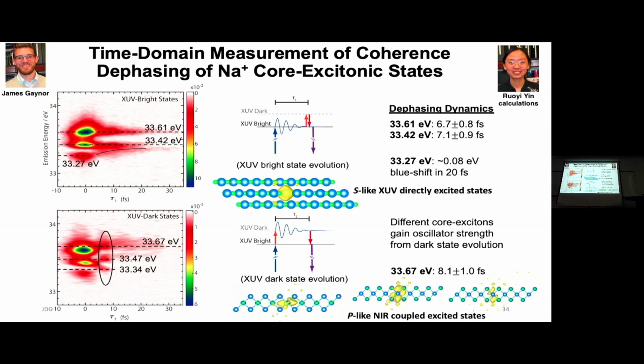residing on multiple atoms. And so, for example, it could start in one set of orbitals, and by collision or by interaction with the solid, it could change from a P-like this way to a P-like that way, and it might have a slightly different energy, and the energy would go to the lattice. So we believe all of these features are real.